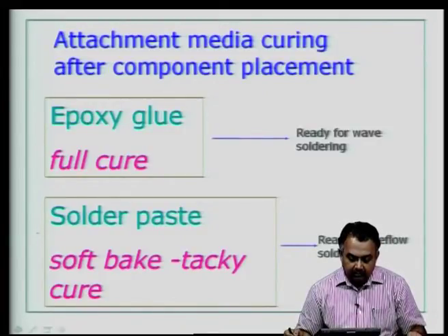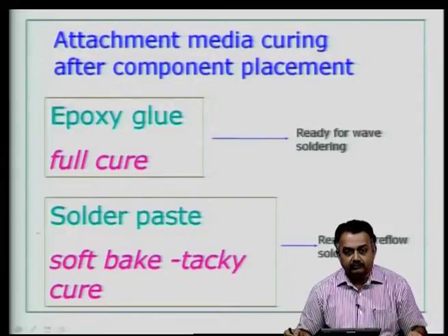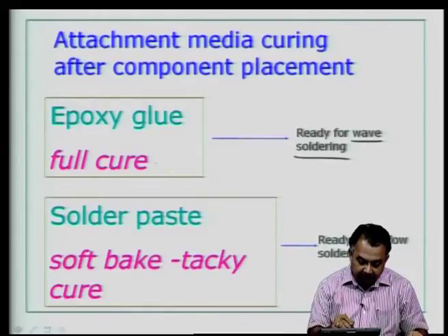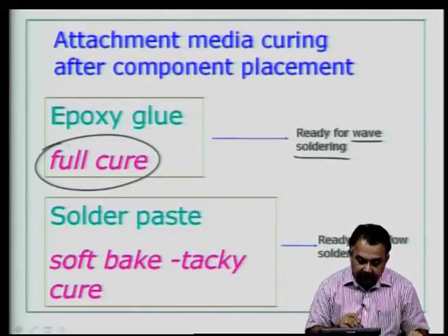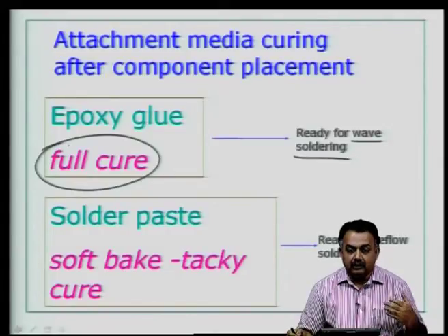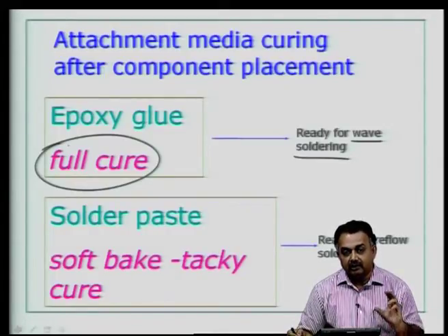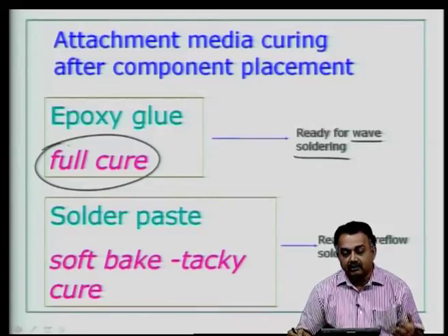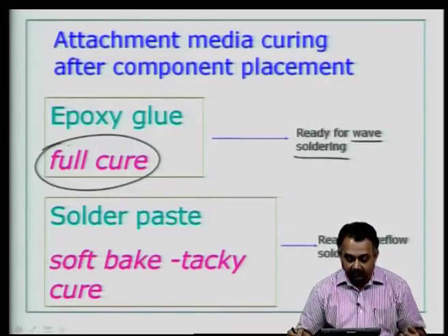Now, if you have used an epoxy glue and you are going to use a wave soldering process, you have to make sure that the glue is fully cured. Okay. It should not be tacky cured, it should be fully cured, and that full curing makes sure that the component is held firmly on the board during the wave soldering process. Otherwise, you will miss out on the components, and the cured epoxy will not be affected by the temperatures or the material during the wave soldering process. So, that is an important criterion.